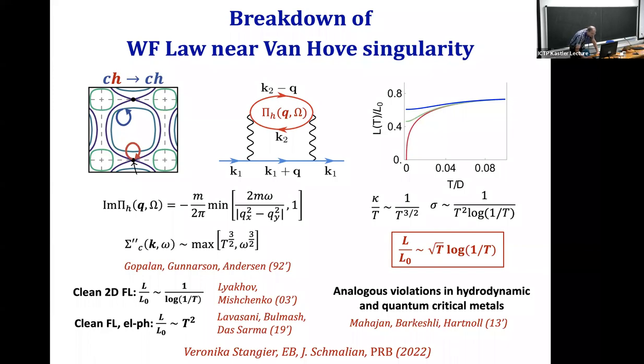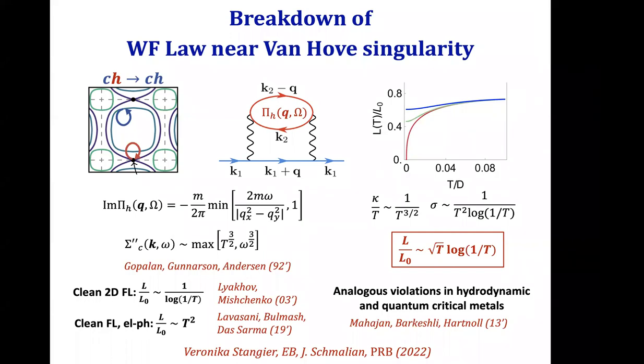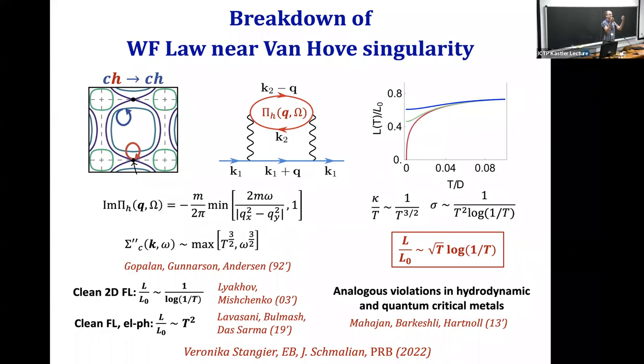Given the high density of states of the Van Hove singularity, why don't we also consider the hot to hot scattering process? That's because most of the electrical and the thermal current is carried by the cold electrons. This is what you might measure if you measured the single particle lifetime of the hot electrons. But we're interested here in the transport properties. So it's really mostly the cold electrons.